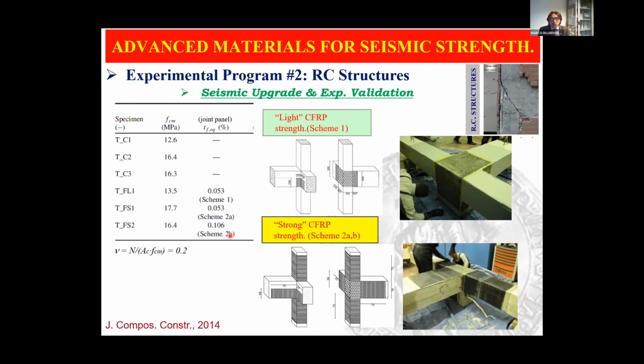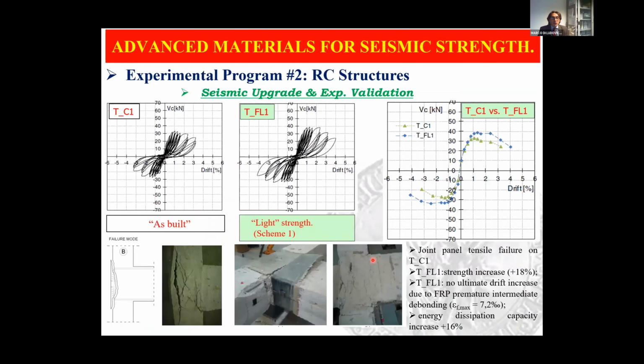Scheme 2A and 2B differ because in the case 2A we have 1 layer of reinforcement on the joint panel, while in case of 2B we have 2 layers. So I will show briefly the experimental outcomes. This is the control specimen, which failed due to shear cracks in the joint panel.